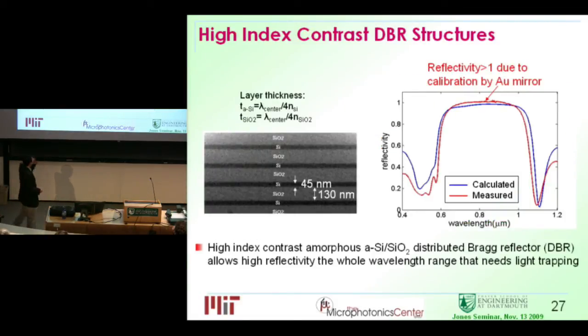So what is a DBR structure? Distributed Bragg reflector is actually a near perfect mirror. So if we make two materials, each one with thickness having a center wavelength, for example in this case about 0.8 micron, and the thickness is this wavelength divided by 4 divided by the refractive index, you get a very broad reflection spectrum in the range that you need